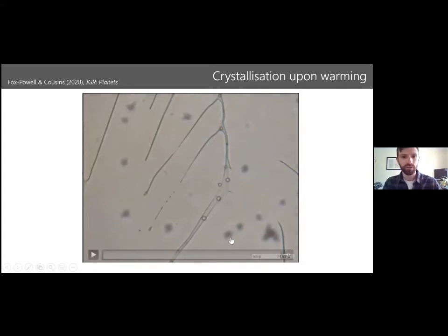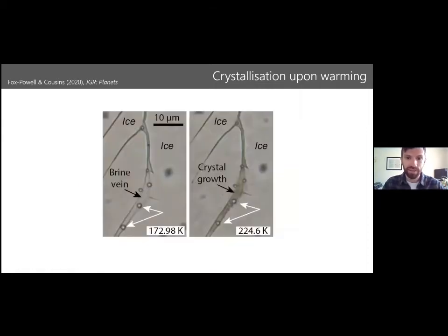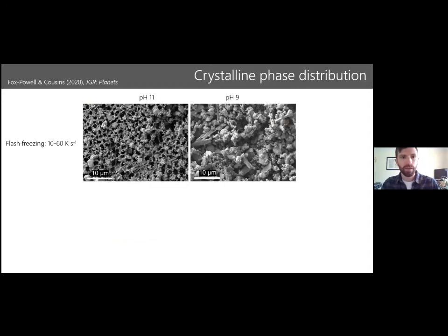That happens if fluids are rewarmed. So this is a video I'm going to play. This is an optical microscope image. You can see a brine vein in the center here, which has gone through this supercooling. There's no crystalline salts there. But as you warm it up gradually, well below the temperature that ice begins to form, you see this yellow-orange crystal mass propagate through the brine vein. So crystalline salts are forming there. And if you didn't see that video, there are some stills here that show how, well below the temperature of ice melting, we have crystallization.